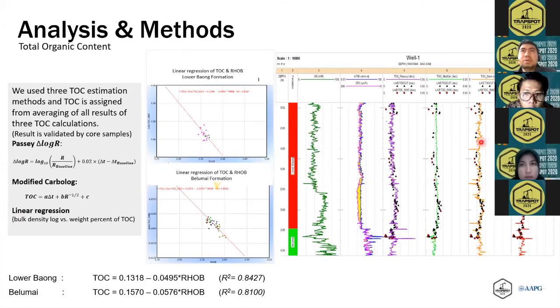And we also calculated from the Passey method. The Passey result is quite interesting, but from the Carbolog, it's quite challenging to see any kind of behavior. So at that time, when I evaluated the TOC, I did an averaging between the TOC from the density and from the Passey, and the average of these I used for my final model.